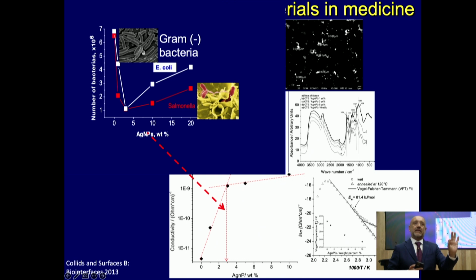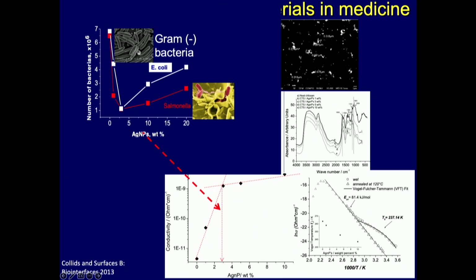By understanding the proper manipulation of percolation concentration, and from that knowledge, build up knowledge to understand that the presence of ionic silver versus just pure metallic silver makes a big difference, and we're trying to combine in a library of proper applications because the literature is so deceiving, even in high-impact journals. They completely overlook this kind of phenomena. What I'm trying to say is, if you have not only the proper concentration, but the electronic structure, but also the balance between ionic and metallic silver, you will lose that battle.